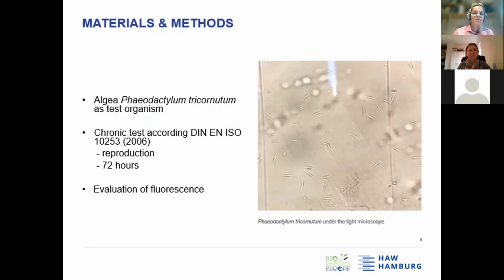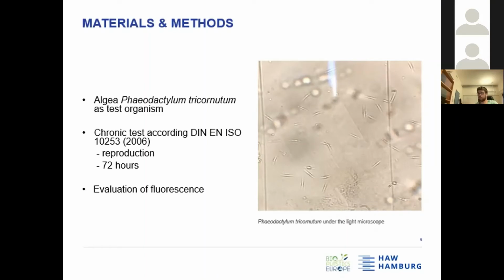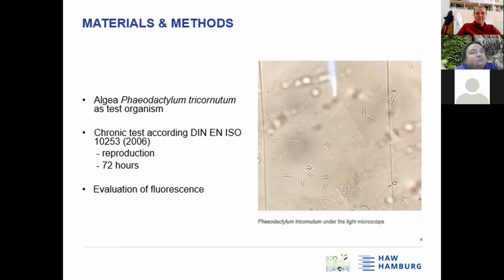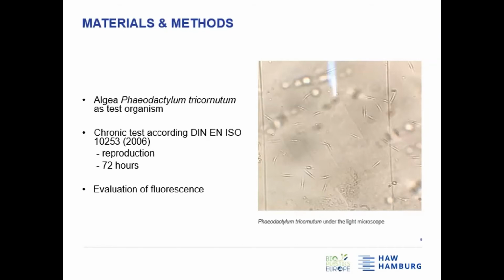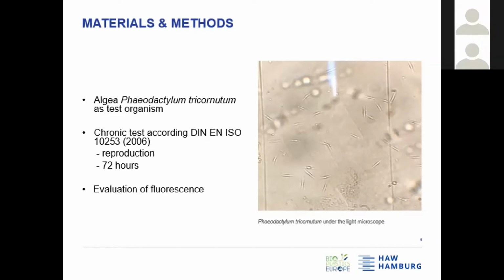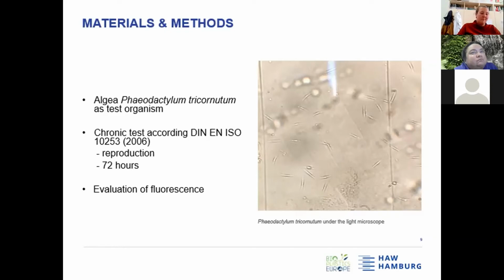Yeah, and in addition to the daphnid tests, we also carried out tests with the marine algae Phaeodactylum tricornutum. This is a microalgae belonging to the group of diatoms. And on the right, you can see the algae under the light microscope with a magnification of 400. These tests were carried out according to ISO 10253 from 2006. This is nearly the same as OECD guideline 201. And the test lasts 72 hours. And during the test, the reproduction of the algae was observed every 24 hours. And this is done by the evaluation of the fluorescence of the algae.